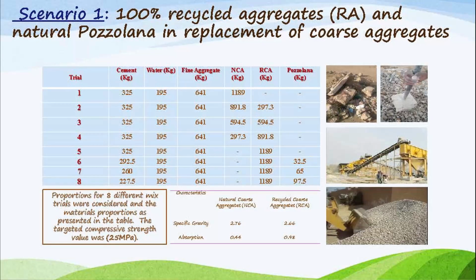If we compare about 8 scenarios at 7 and 28 days for compressive strength, the results show that 100% recycled aggregate and 10% pozzolana is the optimum result. If we use recycled aggregate in the concrete mix, we can use it with 10% additive for cement. We have the optimum results. For the slump test, or workability test, for concrete, we also find the optimum result with 100% recycled aggregate and 10% pozzolana.